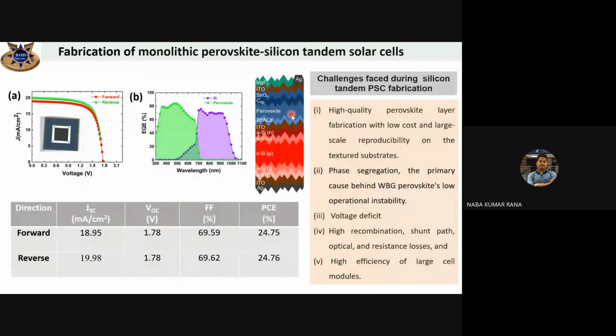And recombination is also a big problem in perovskites, because if there is some pinhole inside the device or in the film, the top electrode will connect with the bottom electrode, and then the device will be short circuited. Approximately we have fabricated 300 to 400 devices. After that, we were able to fabricate our large area silicon tandem devices. This is the highest efficiency device in our lab, and the maximum area is 1 centimeter square. But we try to increase our fabricated device area because in practical application we have to use large area devices.